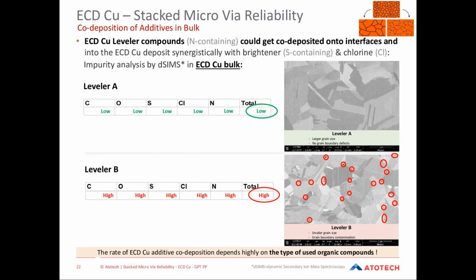Here, to show you one more example about our studies, two electroplating copper processes in comparison. These are both processes from Atotech. So we have a process running with the so-called leveler A here. And you see the image for the leveler A on the top left side of this slide. And this is a typical image of the copper crystal structure of a very clean copper plating process. So this is an image of the bulk of this electroplated copper deposit.